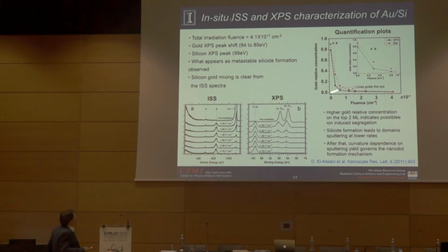And if we go back and correlate the formation of the structures of the nanopattern, we find that there is a very strong link, not only with the presence of a metal there, in this case gold, but in fact the concentration. It's only about 1 to about 3 atomic percent of that metal that induces that instability.